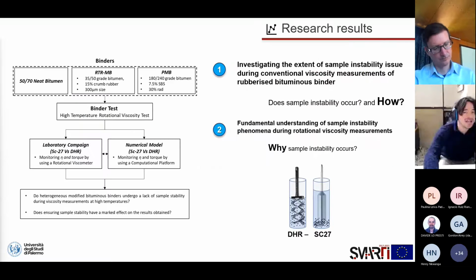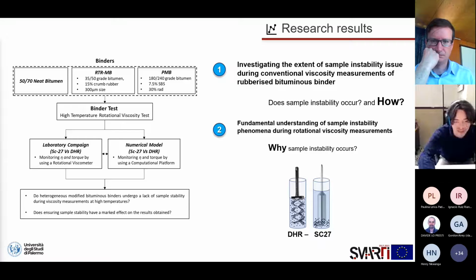In the first part of the research, the idea was to provide a deeper understanding of the before-mentioned phenomena, such as phase separation, sedimentation, agglomeration, by using a computational fluid dynamics model to simulate the laboratory test and use innovative visual aids to monitor the sample stability of heterogeneous bituminous binders during rotational tests. The numerical analysis was also complemented by a laboratory campaign to provide further details about the sample stability phenomena during viscosity measurements of heterogeneous bituminous binder by comparing a conventional standard testing setup, such as the standard spindle 27, and a dual helical ribbon previously developed during my PhD study.